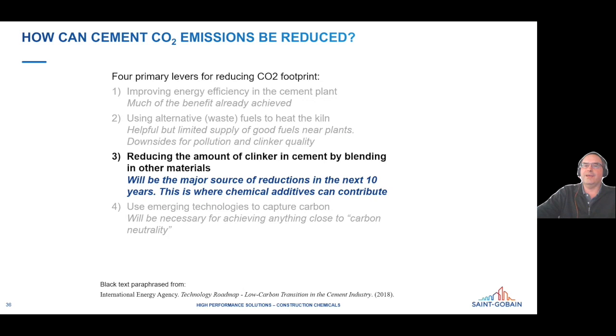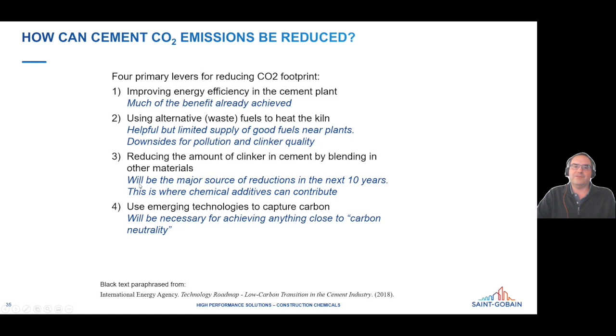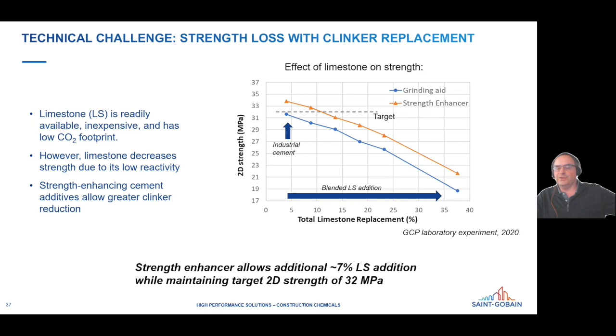So if you can make concrete or cement using less clinker, then you're able to reduce the overall CO2 footprint of whatever application, the road or the building that you're making will then have less clinker in it. And this is really the easiest way for us to reduce it right now, and maybe for the next 10 years or so. It does have its limitations. And if we want to get anywhere near carbon neutrality, we're going to have to move down to number 4 there and capture that carbon. And that's really a separate topic. But for now, we can make a good dent in the footprint by just making concrete with less clinker. This plot here is just showing what happens when you start reducing the clinker content.